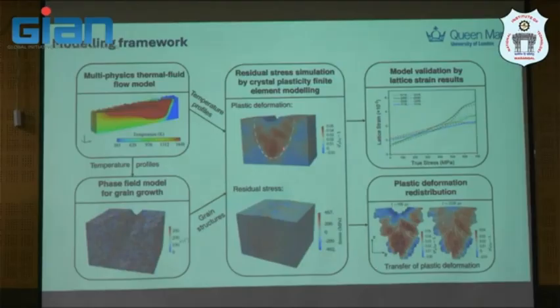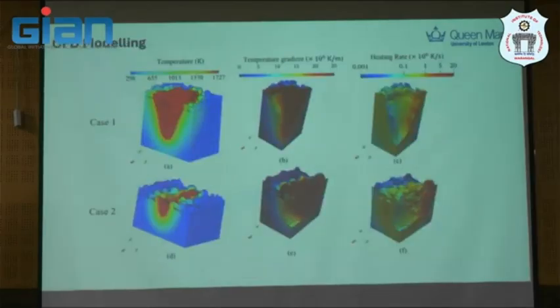It's everywhere. And I want you to notice that this map of residual stress is not the same as the welding residual stress profile where you get compressive and tension. That's because it's actually everywhere. You see this profile because of the different residual stress in type 1, type 2, type 3, inside the grain and so on. I don't want to mention much about that. And this can be predicted, but it's not easy. But this is what they do.